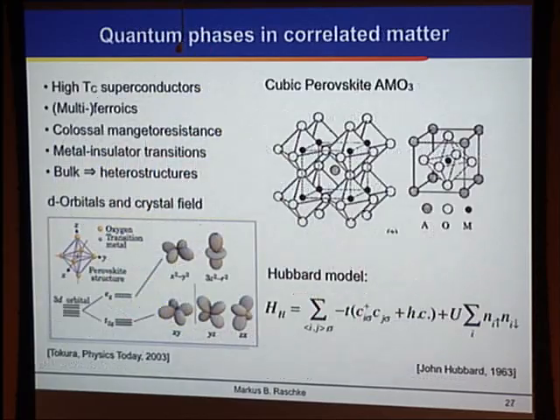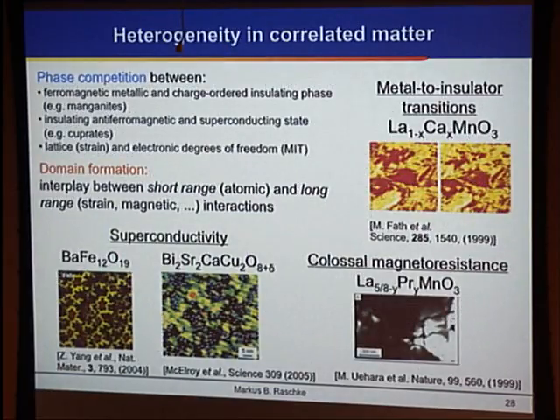So this has been proposed a lot, the ability to control quantum phases in correlated matter by light, and it is responsible for a lot of the relevant physics of the d electrons on these transition metal ions, which often characterize, in a perovskite structure, the types of behavior. And people have seen, associated with a lot of these types of quantum phase transitions, domains, typically in transmission electron microscopy or STM. Here are some of the famous historic examples, where it was thought that responsible for this domain formation associated with the quantum phase transition is the interplay of this short range, orbital type interactions, and then these long range interactions, in particular strain and magnetic domain formation.